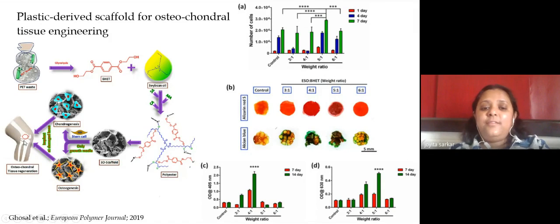Okay, so in very severe cases of arthritis and all, along with the cartilage, the bone also starts to degrade because of the friction that is created between these two bones. So such type of scaffolds which are used for both osteochondral tissue engineering could be a very good source for the regenerative medicine of such severe cases of arthritis. And we can see that how the cells nicely proliferate in the scaffolds that are created. These ratios actually show the ratio of BHET to soybean oil that was used to form the polyester, and we can see that 4:1 to 5:1 ratio of BHET to soybean oil actually gives a quite good result.